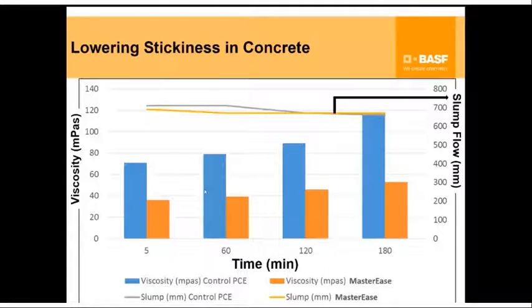And then that allows us to basically look at viscosity over time. And what we see here is that a normal, so if you don't have any PCE in a cementitious mixture, you will still see that your viscosity keeps increasing, okay? So if you do a V funnel of a normal concrete at the same workability, so let's say your workability is 600, 600, 600 over, let's say 3 hours, right? You will still see that the V funnel times will increase for the same workability level over time.